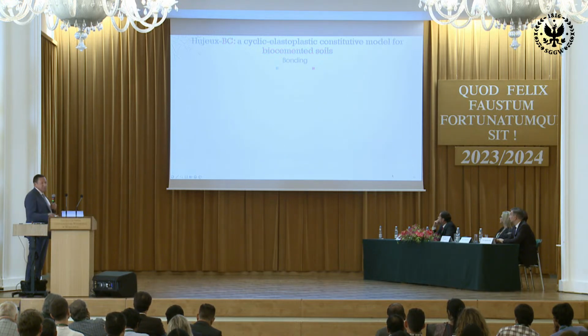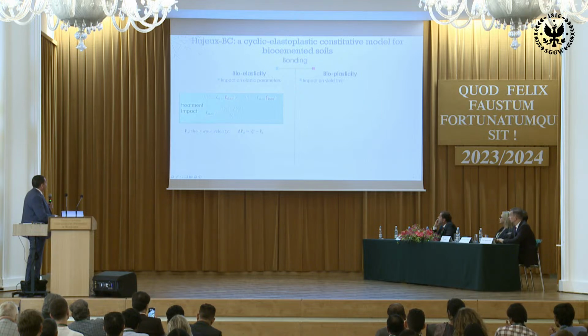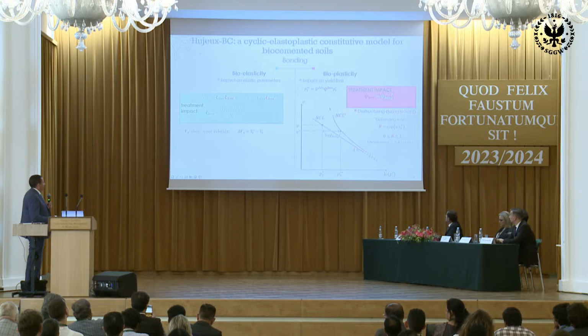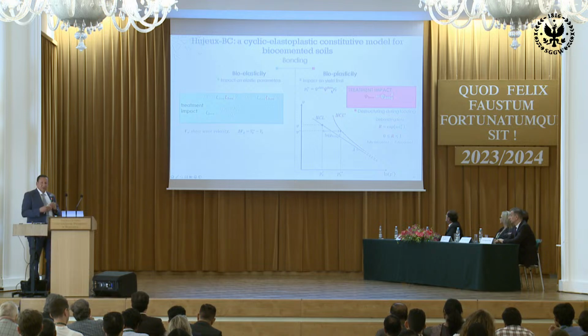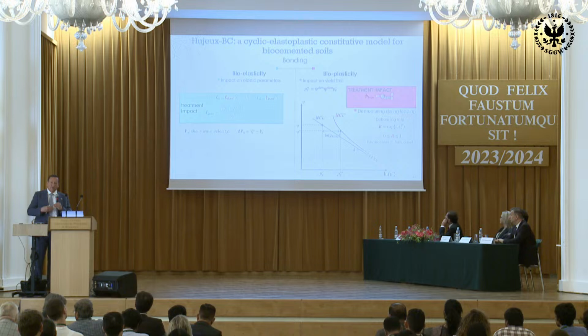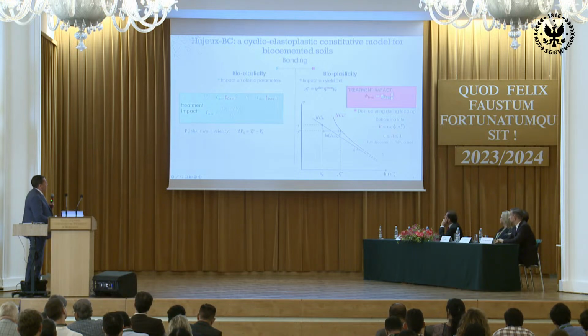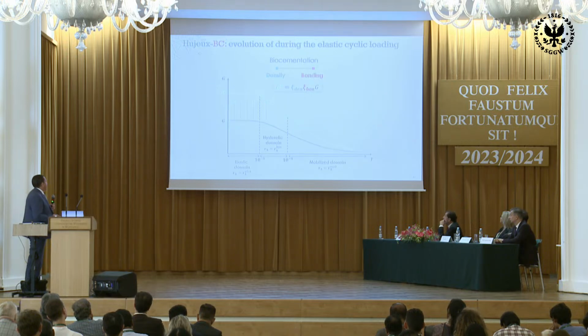The other aspect is bonding, as I mentioned. So the bonding, we do also for elasticity and plasticity. Again, we introduce a new coefficient for the elastic parameters. What's more important for the plastic part is that this bonding coefficient represents the fact that at very high shear stress, we will have destruction of those bonds. So we will move from a larger normally consolidated line to come back to the untreated normally consolidated line, like we do for structural materials, for instance.